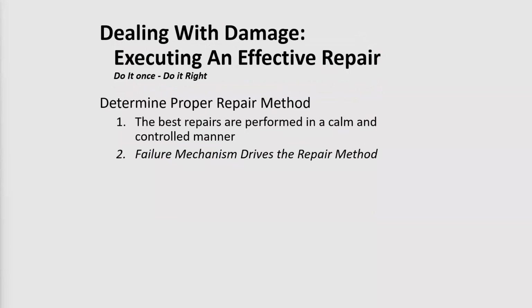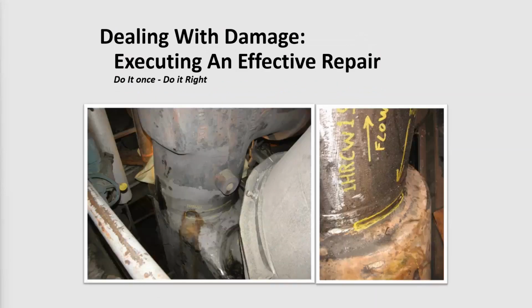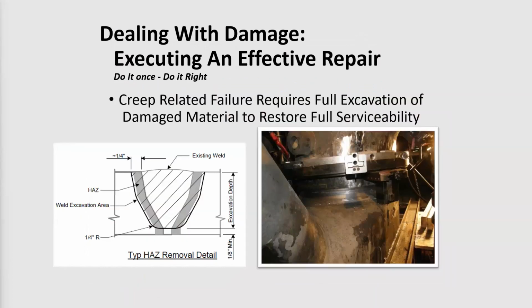The failure mechanism is going to drive the repair method. I think from what we've discussed, that should be apparent. When creep damage is involved, oftentimes, particularly if the damage is associated with some portion of the heat affected zone, then part of the success of the repair is going to be ensuring that all of the damaged material is fully excavated, which means extending the excavation beyond the limits of the heat affected zone of the original weld.